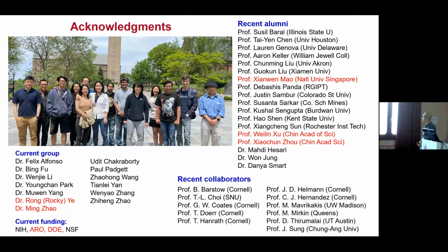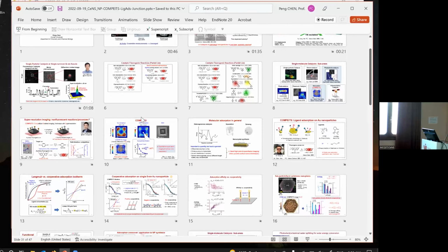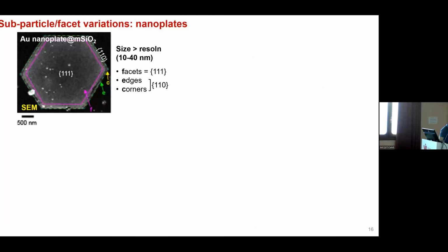So in the case of the ligand exchange for the flat gold surface, do you also have a porous layer? Yes, we actually do. I didn't cover it; I went through it quickly. For example, in this particular case, the particle is covered with a very thin shell of mesoporous silica, okay, and we detect the product in the shell rather than on the particle surface directly.